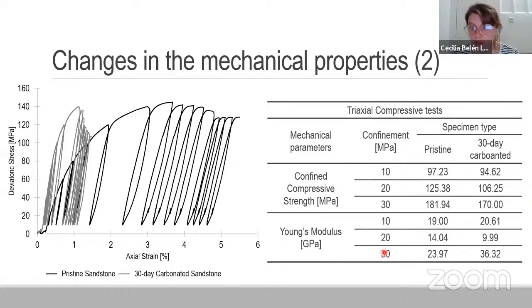In the triaxial compressive test, we observed that the Young's modulus increased, meaning that instead of becoming more ductile, the behavior became more fragile. The main reason for this is that we believe the rock, when it is not confined, as it has a lot of discontinuities, breaks in a more fragile manner.